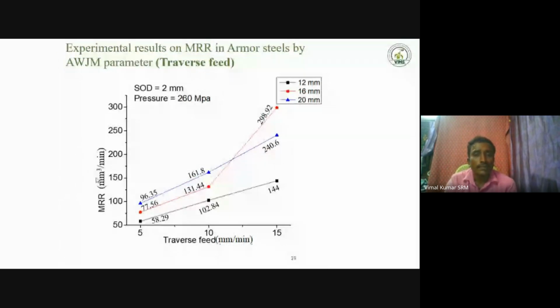Here are the experimental results on material removal rate, MRR, by traverse speed. Previously we talked about how the kerf angle is influenced by SOD, traverse speed and pressure. Now we look at material removal rate, which is influenced by traverse speed. If traverse speed changes for three different thicknesses, the material removal rate is directly proportional to the traverse speed. If traverse speed is increased, material removal rate also increases. Black is the 12 mm plate, red is the 16 mm plate, and blue is the 20 mm plate. We fix the SOD and pressure input values and change the traverse speed, and the material removal also changes.